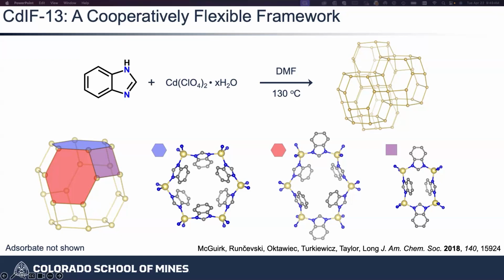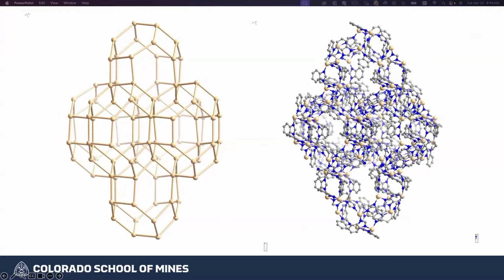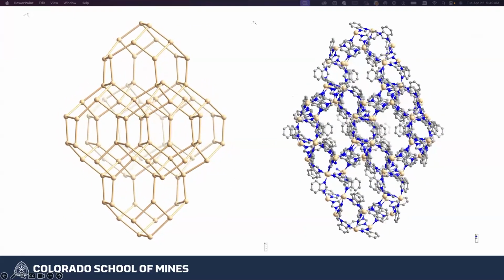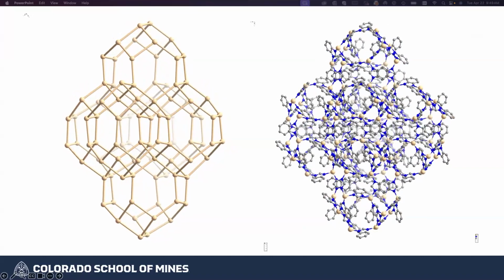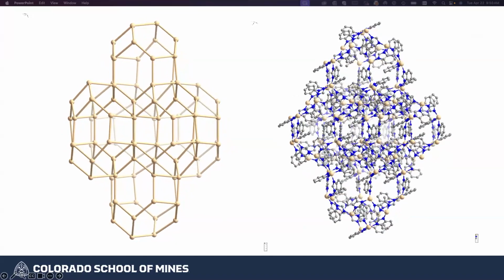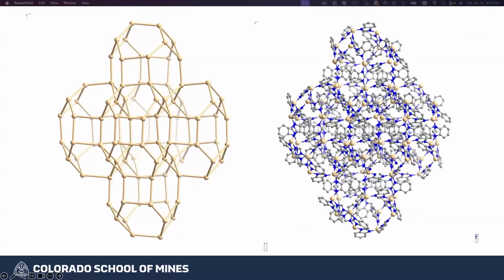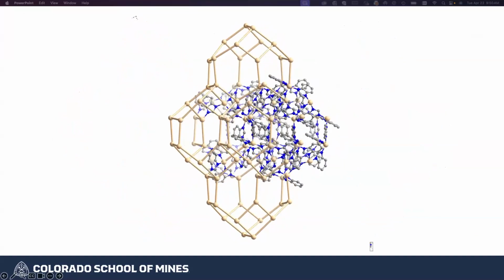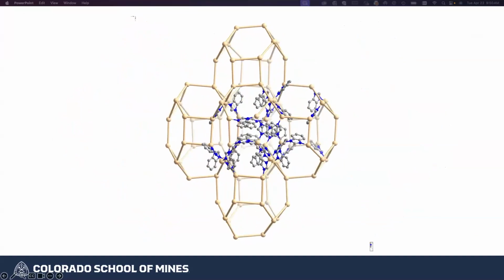And so these structures that I'm showing here, or this is all one structure, comes from single crystal originally. And we have all these different points of view because this structure is kind of hard to look at, in that we have these repeating cages that I've shown again here. Then in these cages, we have these individual faces. But really what we have here are these rings of coordination with those benzimidazolate linkers sitting at around a 45-degree angle. And like I said, the structure is kind of hard to look at because it is relatively low symmetry, and you have a lot of these dangling organic systems. And so that, combined with the visual density, we like to do a lot of different representations of the system. And also we like to play games where we take the linkers out to correlate the linkers with the coordination lattice itself.